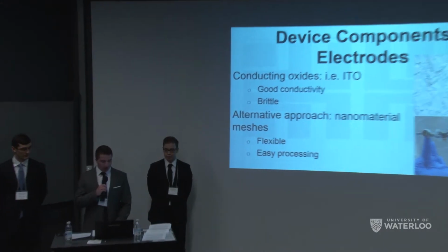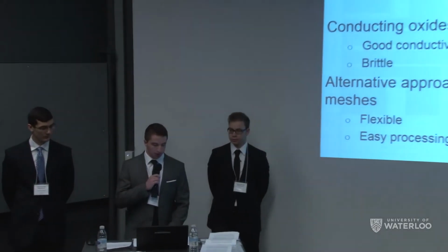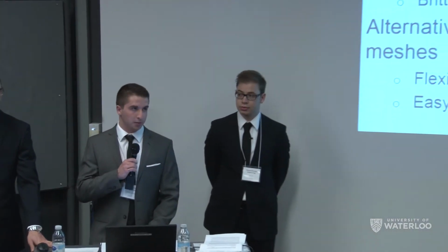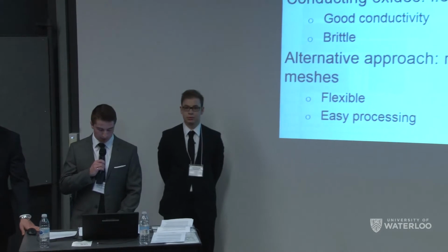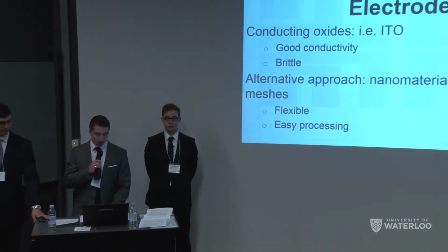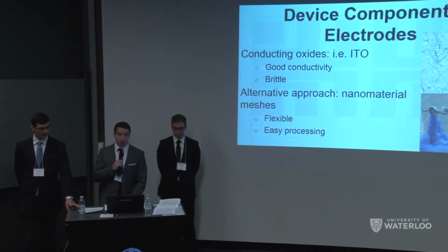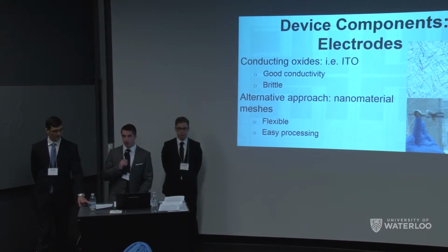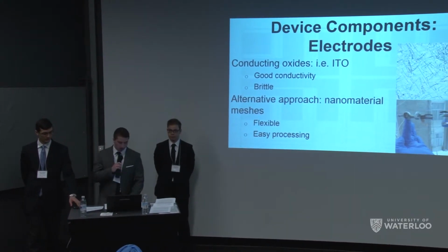These nanowires form a mesh when deposited onto our top substrates, as shown in the micrograph in the top left-hand corner of our slide. We then sinter them for better electrical properties, such as reducing the resistance of the nanowires down to less than 20 ohms per square. We are also taking advantage of the flexibility of the silver nanowires by depositing them on our plastic substrate. We are able to deposit the silver nanowires via roll-on methods onto our plastic sheets, which also enables reel-to-reel processing as a scale-up method.